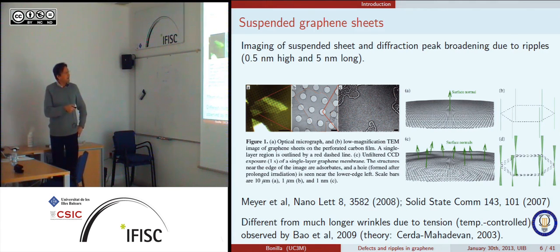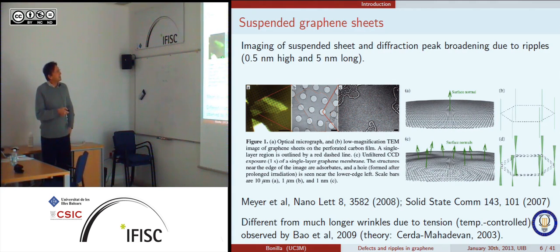And these are images with different resolution. So these are the holes. Now what you do is you put here your membrane. This is the one monolayer. This is bilayer or something. Then you use the transmission electron microscope to irradiate the borders strongly enough so that you create some impurities, and these pin down the graphene monolayer, because otherwise it crumbles and you don't see anything.